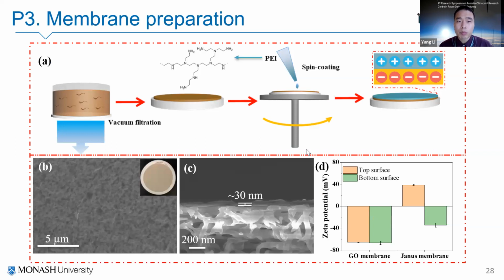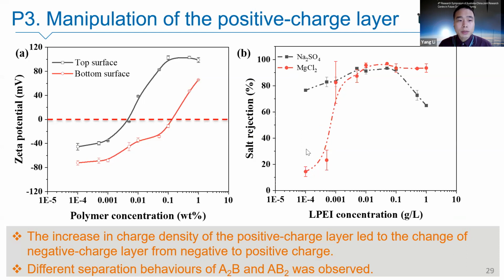For the membrane preparation, we use vacuum filtration, same as the previous two projects. After that, we adopt the spin coating method to modify the surface with the positive charge polymer, PEI. After surface modification by spin coating, we found the membrane is around 30 nanometers thick, with a positive surface charge on top and the negative layer below. When we tune the charge properties by different polymer concentration, we found that with the increase of polymer concentration, the top surface charge slowly changes from negative to positive. Similarly, the bottom layer also slightly changes from negative to positive charge.